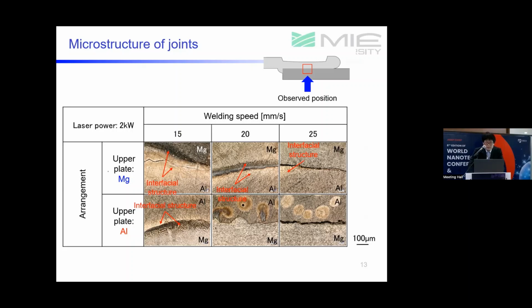As shown by arrows, a black interfacial structure was observed on the magnesium base metal side, and a white interfacial structure on the aluminum base metal side. In addition, from the size of the area shown in the light blue region, it was found that the amount of interfacial structure generated was smaller under the condition with aluminum as the upper plate.